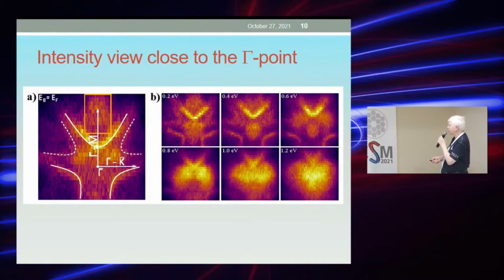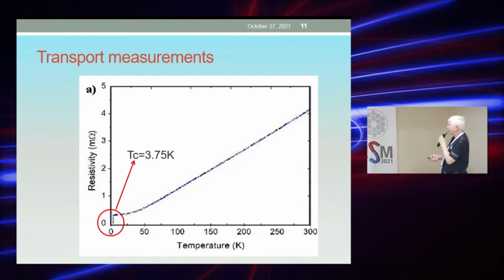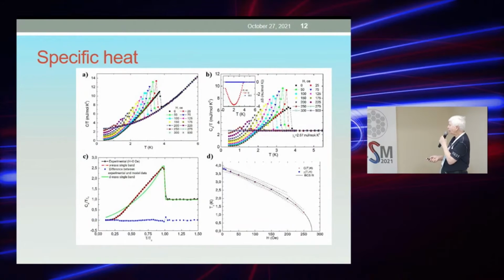The energy band structure close to the gamma point is well identified. It's fully consistent with theoretical calculations, and so we move to transport measurements. In transport measurements, we see a sharp superconducting transition, and we focus on the specific heat measurements, which could be traced as a function of magnetic field. The magnetic field suppresses the transition and shifts it to the lower temperature side.